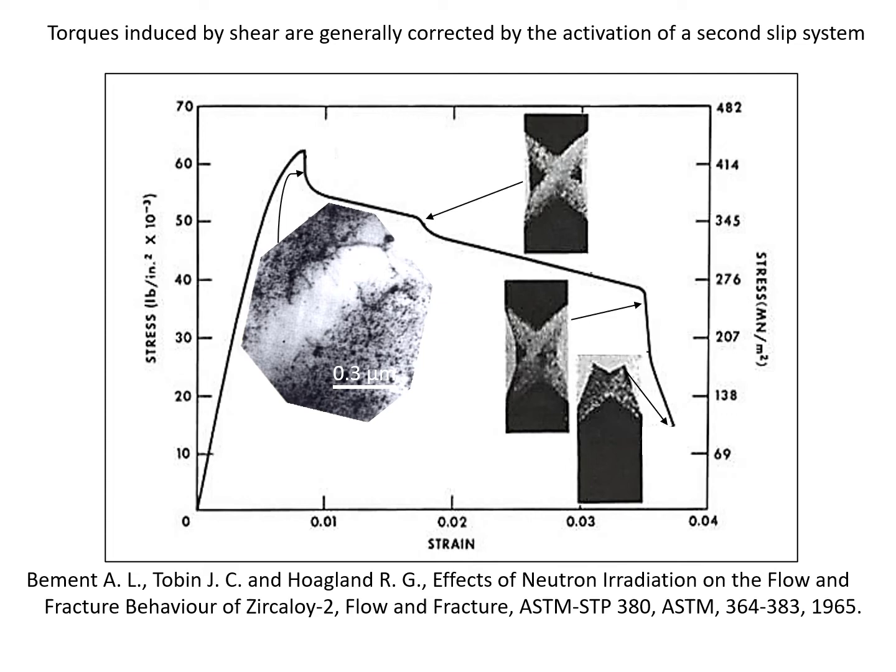And as we described earlier, with that secondary slip system to bring the tensile specimen into conformance with the load line, you then have options for a second slip operation, the introduction of a secondary slip system, to bring it into conformance, and this generally shows up as a second load drop. And there we see it. And eventually the material will neck and fail.